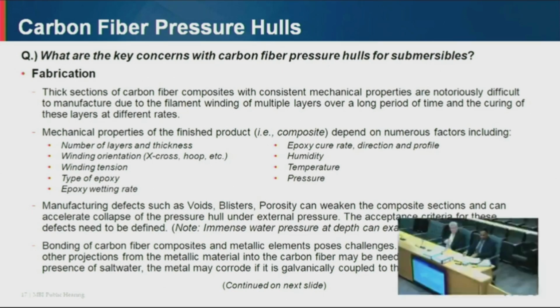Okay? So in a thick carbon fiber pressure hull, there may be several layers of carbon fiber composites, and these layers cure at different rates. So what you will have is several layers with different mechanical properties since they were cured at different rates at different times. Okay? So manufacturing a thick section of carbon fiber composites with consistent mechanical properties throughout the thickness is difficult. Okay? So the mechanical properties of the finished carbon fiber pressure hull depend on a number of factors. So these include the number of layers and the thickness of the carbon fiber composites. So the more the number of layers and the greater the thickness, the more difficult it is to achieve a pressure hull with consistent mechanical properties throughout the thickness.